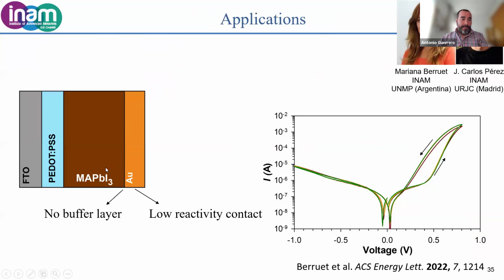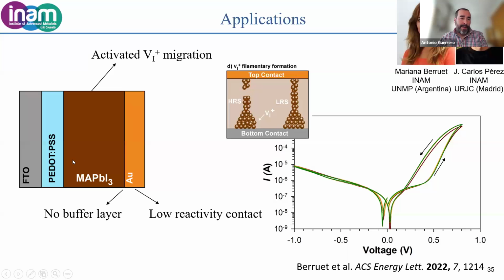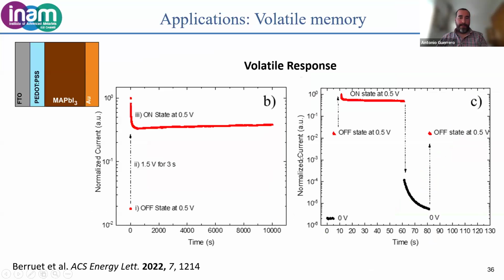So for example, if we take a device with activated ion migration, as I showed you before, like methyl ammonium lead iodide, with no buffer layer and with a contact which shows no reactivity, so that we don't have large reactivity between the gold and the perovskite, we observe this type of IV curve. And here we only have two states, so we can do like 1,000 cycles, and the difference between the on and off doesn't change very much. And then we believe that this is because we are moving the ions inside the perovskite, and we are forming these filaments of vacancies inside, and we can break the filament by reversing the polarity of the applied voltage.